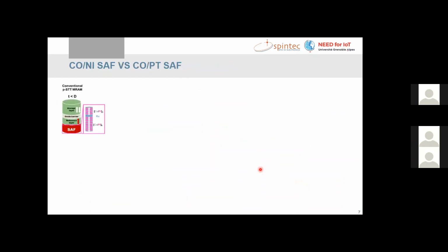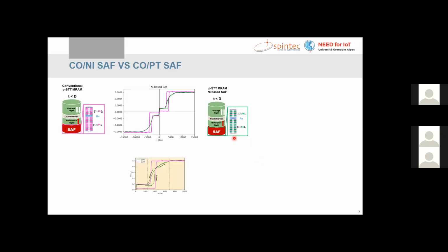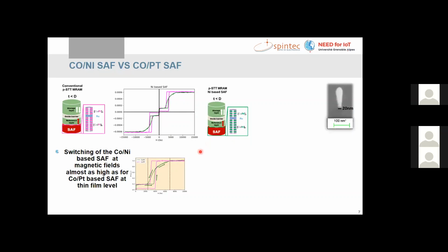So finally, we were able, after some further development, to build the device based on cobalt nickel. First I show you some thin film results at wafer level. And we saw that the magnetic properties of this synthetic antiferromagnet based on nickel were quite similar to the one based on cobalt platinum. And we see that the switching field occurs at a very high field as well. And after, we had to pattern this device into very small nodes. So here you can see we have pillars down to 20 nanometer diameter.